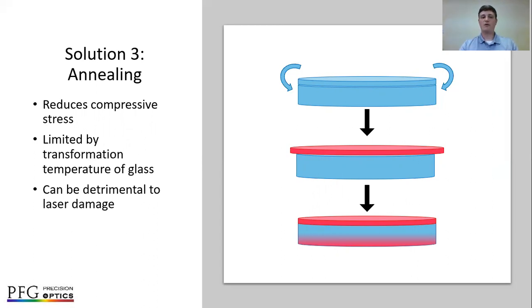You are limited, however, by the transformation temperature of your glass that you cannot exceed. Also, there are some studies that show that the wrong anneal temperature can be detrimental to your laser damage threshold. So you have to be careful when employing this method, but oftentimes it's possible to find the proper anneal temperature and time that will reduce the stress of a compressive coating and get it very near neutral.